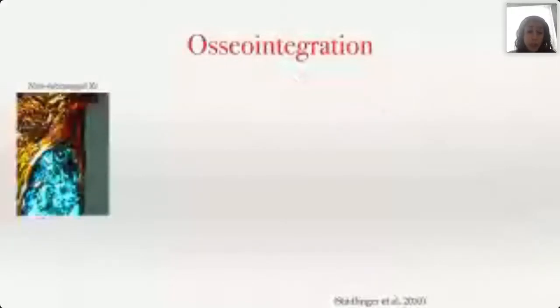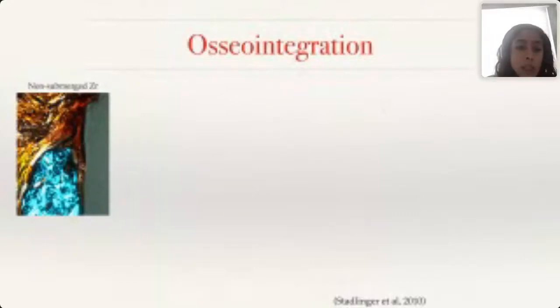This first slide shows the non-submerged zirconia group. These implants were exposed, and one of the important findings was there was remodeling of the bone, with the connective tissue attachment showing dense fibers that were parallel to the surface of the implant and down to the periosteum - not perpendicular, but parallel, similar to what we see around titanium. Because they were non-submerged, they also noticed some downgrowth of the epithelium.